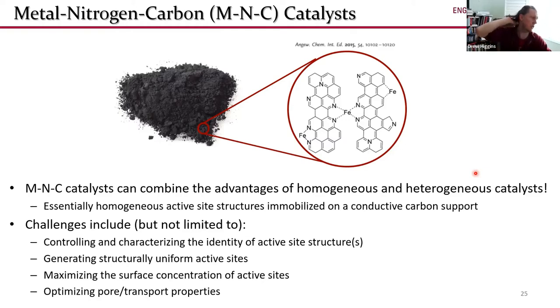But there are some challenges. There are some challenges in terms of the synthesis, in making sure that we form active sites that are structurally uniform, that have high surface concentrations. And then, once we do that, it's really difficult to characterize these atomically dispersed single atom active sites. There are not many characterization techniques out there that are really good for just looking at a single atom and telling us what that single atom looks like, what its coordination environment looks like, what the surrounding environment looks like. So characterizing these materials is a challenge. And I'm going to be talking about that a little bit today.